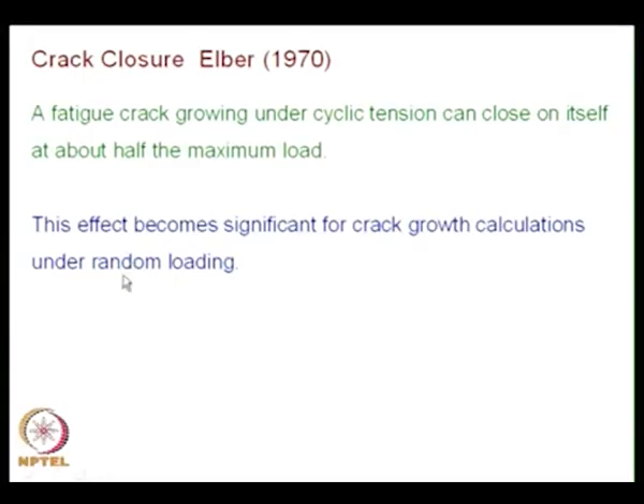So you will have to keep in mind, fatigue is one of the most difficult types of loading that acts on the structure. You will invariably have variable amplitude loading, and one of the difficulties is finding out the actual load spectrum. It is not simple. There are methodologies available, and you have to study the literature and then only calculate the actual load spectrum. So invariably you will have variable amplitude loading. From a modeling point of view, we may study under constant amplitude loading how the crack grows, but if you want to take the knowledge to the field, you will have to account for random loading, and if you go for random loading, you will have to bring in the observations of crack closure into your life estimation calculation.